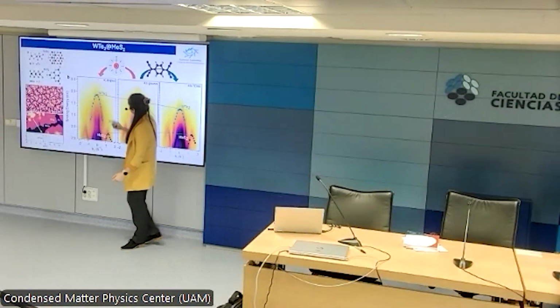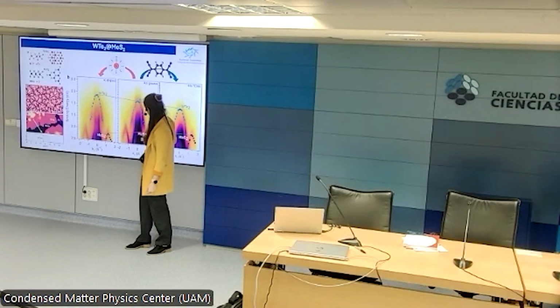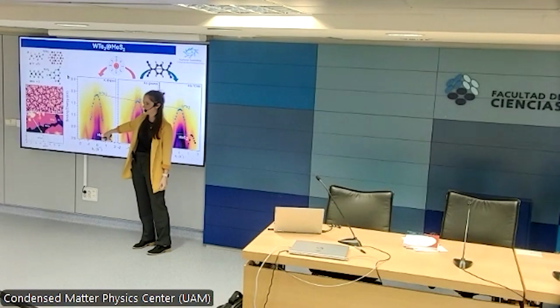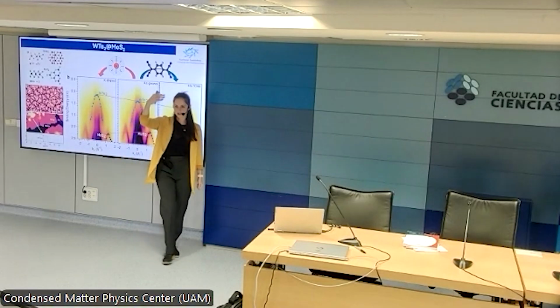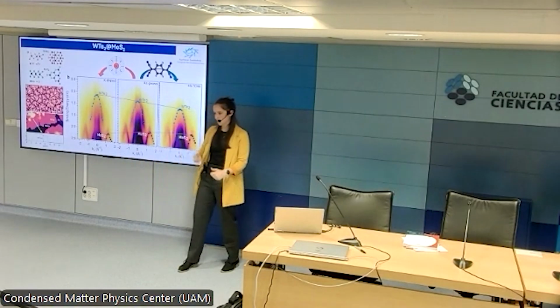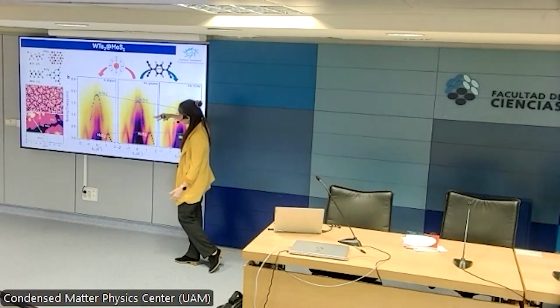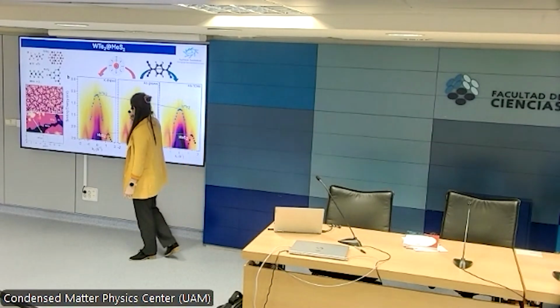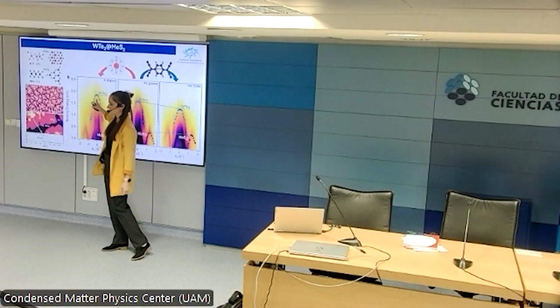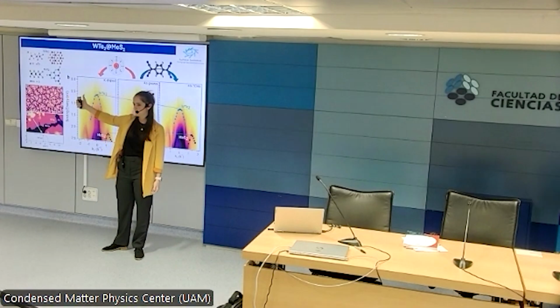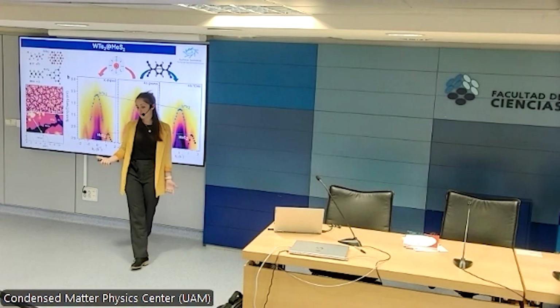Let's look at potassium first. We dope with potassium, and what we see is that the bands of MoS2 shift downwards, which is compatible with the fact that you're adding electrons, so shifting up the Fermi level with respect to the band structure. But then, puzzlingly, the tungsten ditelluride bands go up. And we thought, oh, well, that's because it's closing the gap, maybe.